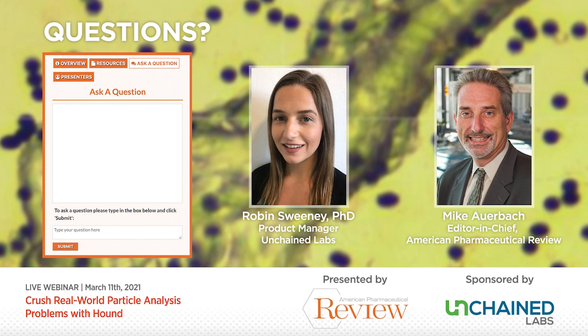The filter round and wet round that I talked about are both gold-coated, and there's a couple reasons for this. First, when you're doing dark field imaging with that 20x objective that's on Hound, it increases the contrast so that you're getting a high contrast between your particles and the background. On the spectroscopy side of things, though, gold is Raman inactive, so the gold coating helps to reduce background noise. That way you're not getting any signal from the consumable itself, and you're getting the cleanest, lowest noise spectrum possible.